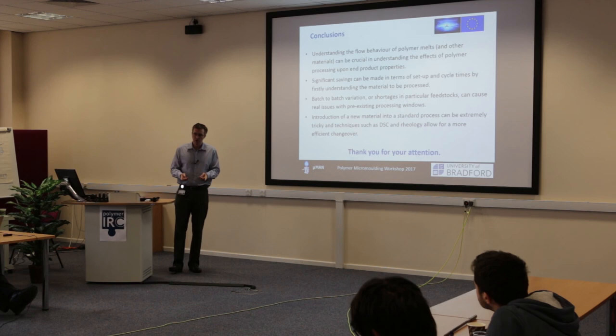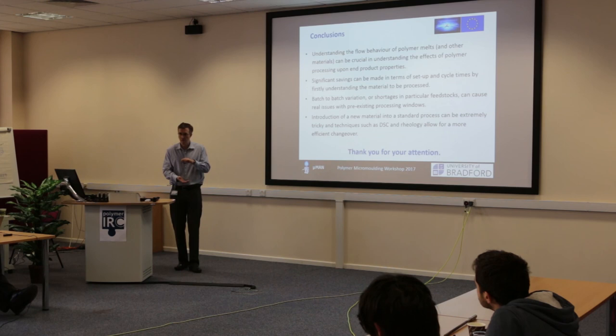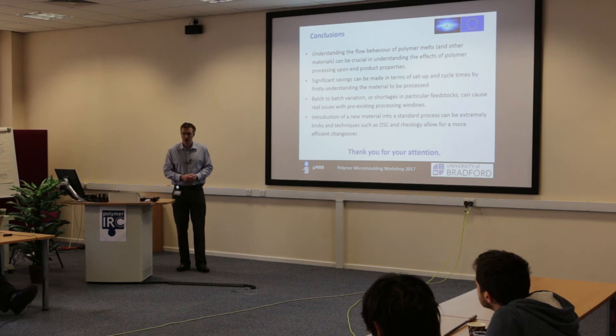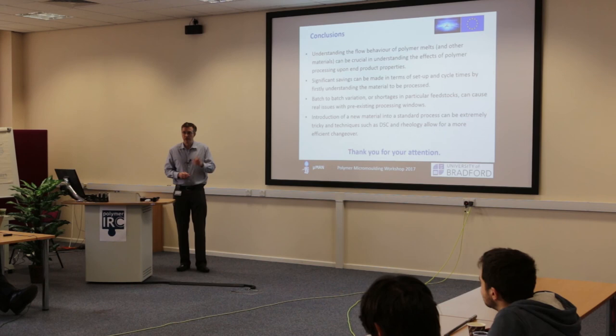We've done research projects with companies that make milk bottles, and they had a drive within the industry to increase the amount of recycled material that went into the plastic milk bottles, but they had to understand what effect that was going to have on their process. We found that after multiple recycling steps, the rheology did change, and they started to behave slightly differently in subtle ways, but enough for them to have to change their process. Yes, I think there is a poster, some work with Nampak.